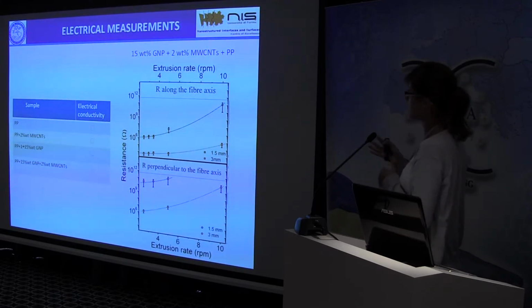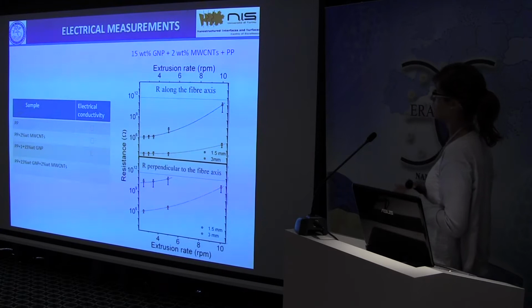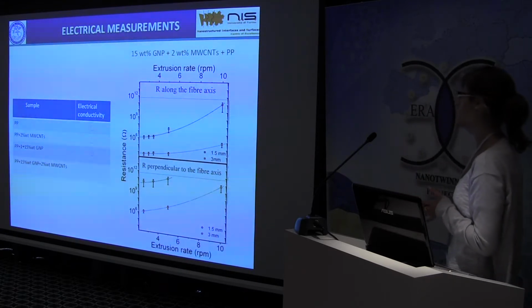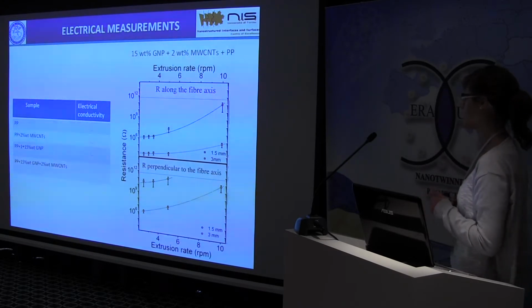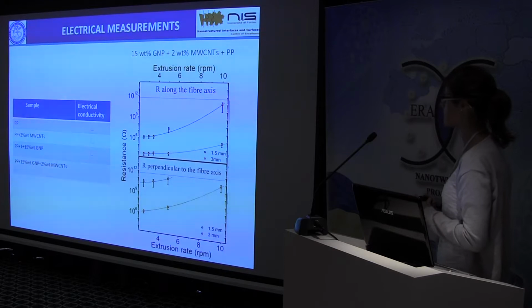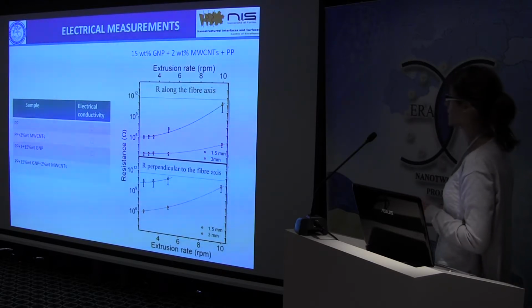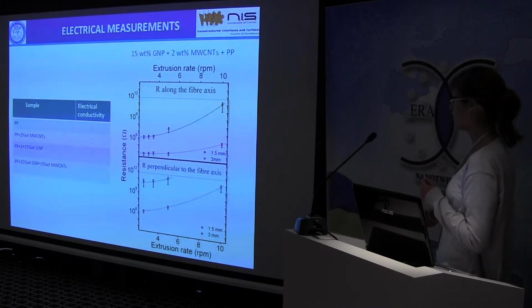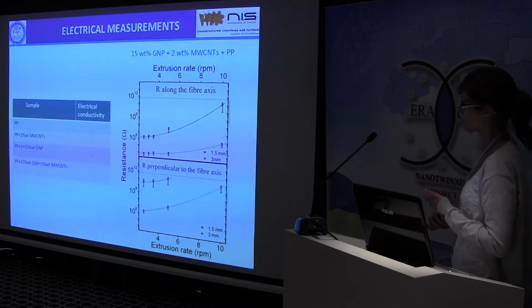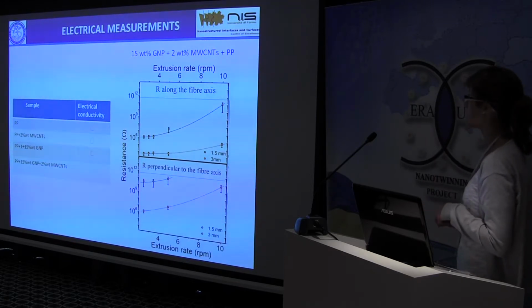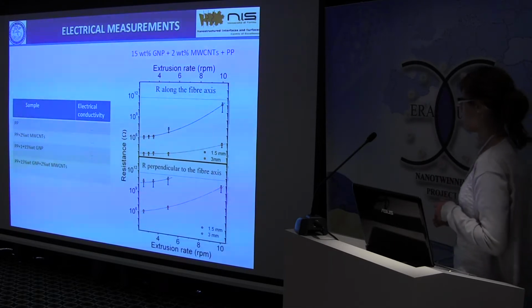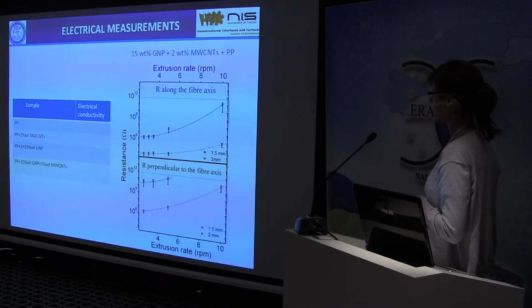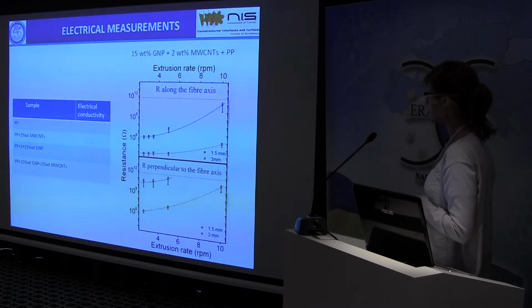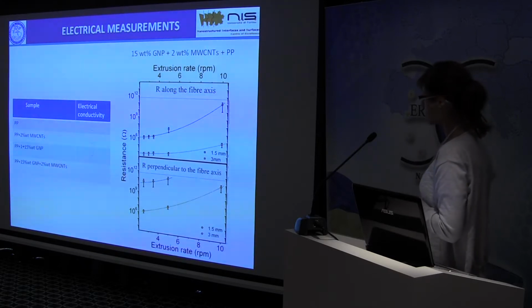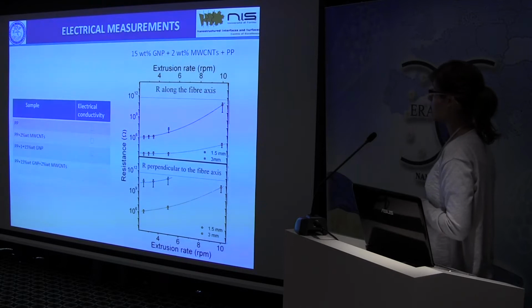These composites were analyzed from the electrical conductivity point of view, and we found out that only the fibers containing both multi-wall carbon nanotubes and graphite nanoplatelets were conductive. So this composite was analyzed to see if the extrusion rate applied during the extrusion phase and the diameter of the fiber could influence the electrical resistance of the composite. And we found out that yes, they influence the electrical resistance, and in particular with a higher extrusion rate and a decrease in the diameter, we have a rise in the electrical resistance.